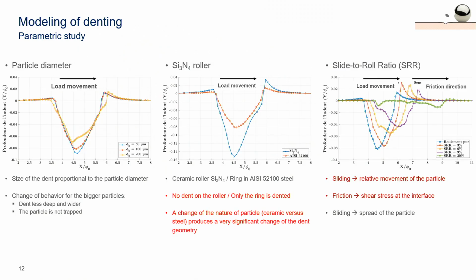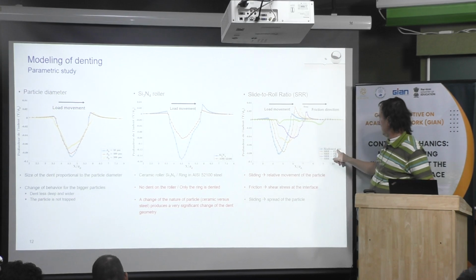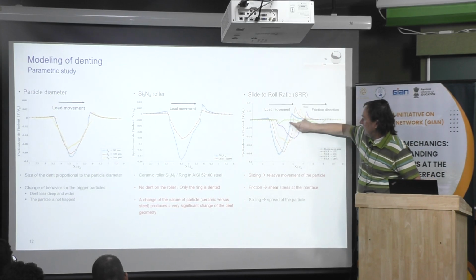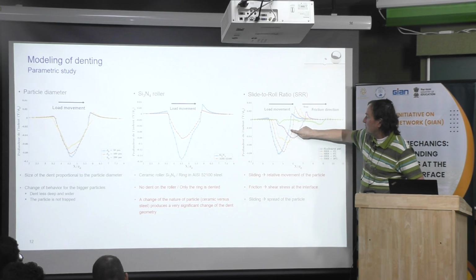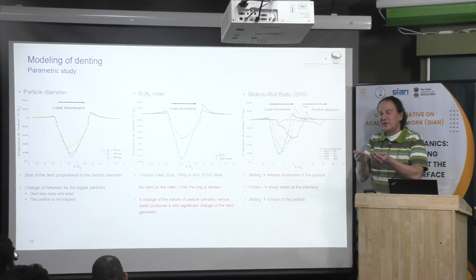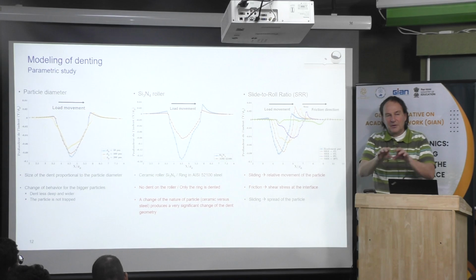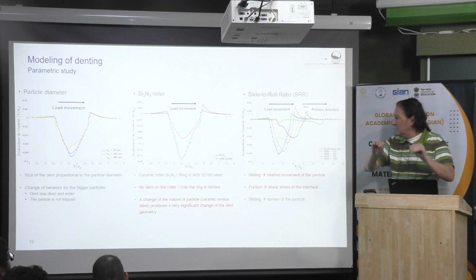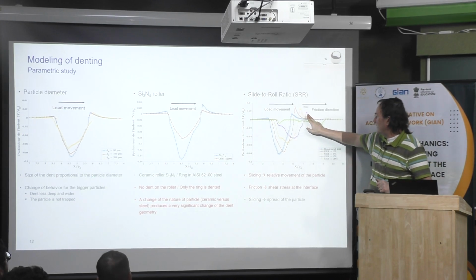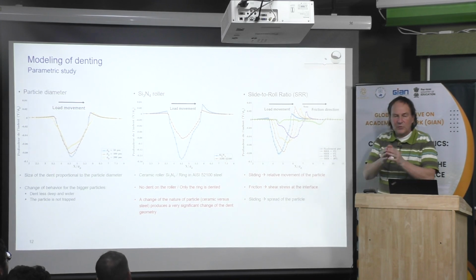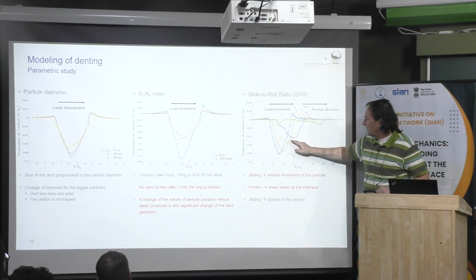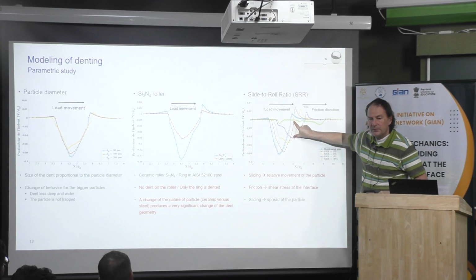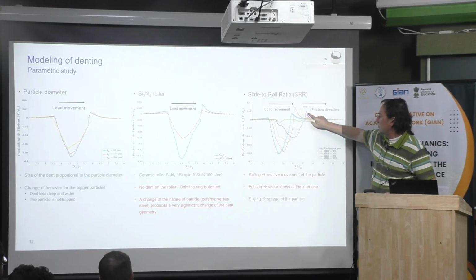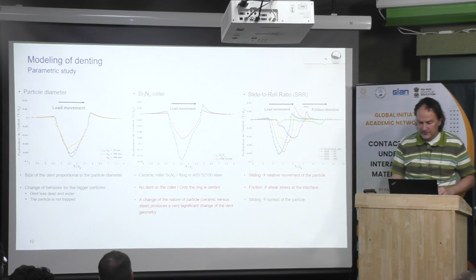And this is the effect of the slide to roll ratio. Then the blue curve here corresponds to something which should be in pure rolling. Okay, this is in pure rolling. And when you increase the slide to roll ratio, in fact, you will have a dent which is larger. You will spread, in fact, the surface defect, and also the shoulder will diminish. And okay, then you have a larger dent, and it will be shallower. And normally, also the shoulder should be smaller.